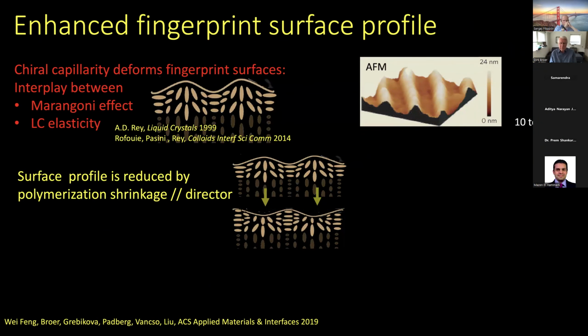Well, this is the switch from flat to corrugated, but actually we were even more interested in the switch from one corrugated state to another corrugated state. And for that reason, we had to work on a principle to develop a film that is already initially having the initial corrugation. Well, if you start making the film as such, I already mentioned the Marangoni effect, you will have a low surface tension in the perpendicularly oriented areas, and you have a high surface tension in the parallel oriented areas. And that leads already to this initial surface structure.